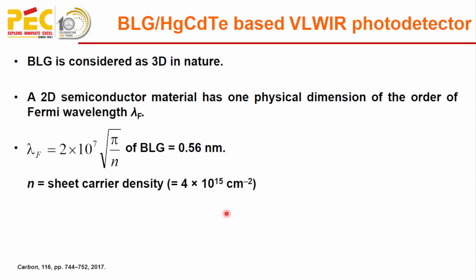A two-dimensional semiconductor material has one physical dimension of the order of the Fermi wavelength, and the Fermi wavelength is given by this expression. In the case of my device, it was found to be 0.56 nanometer, which is less than the considered thickness, that is 2 nanometer, of the proposed devices. Here n is the sheet carrier density, and the sheet carrier density is obtained by multiplying the graphene thickness by the bulk carrier density.